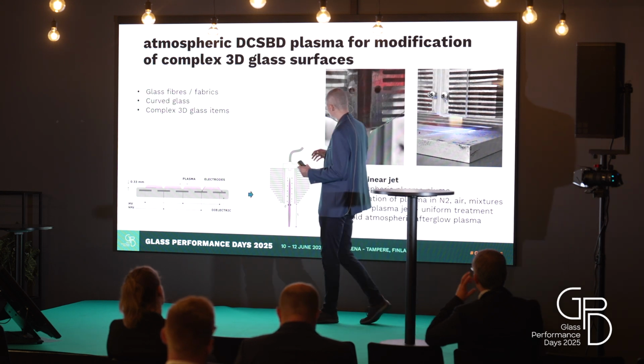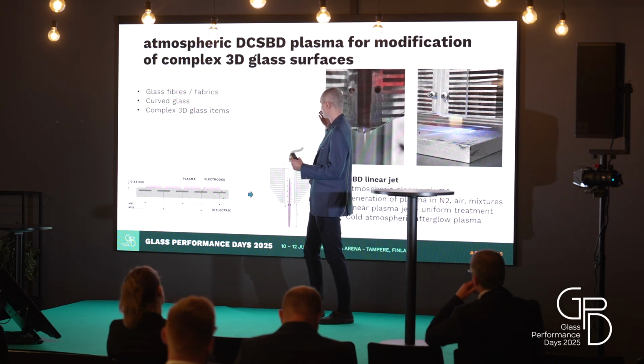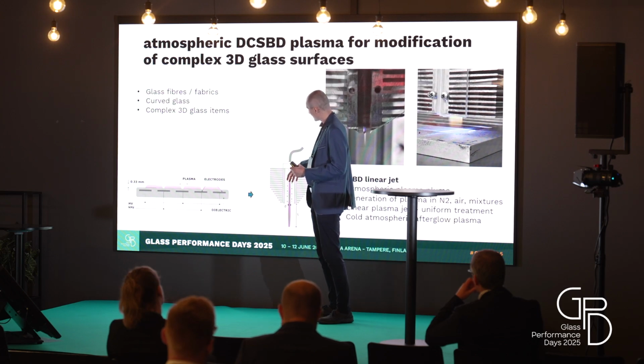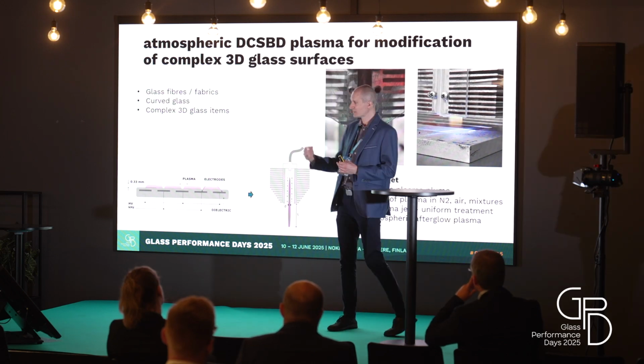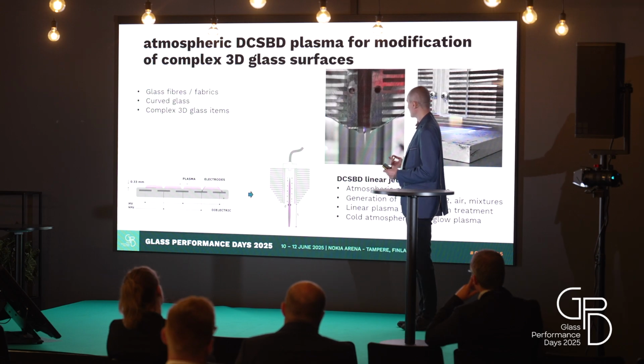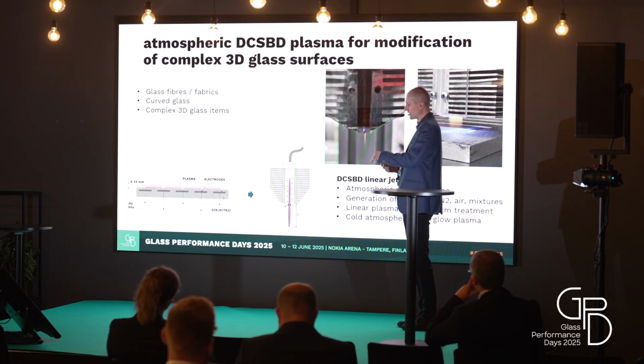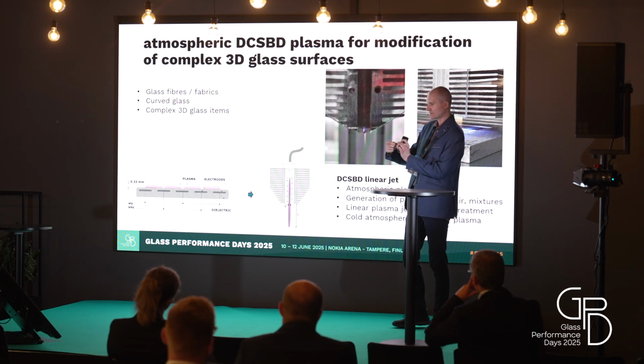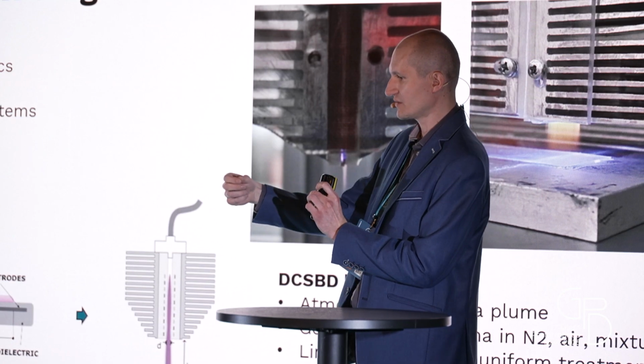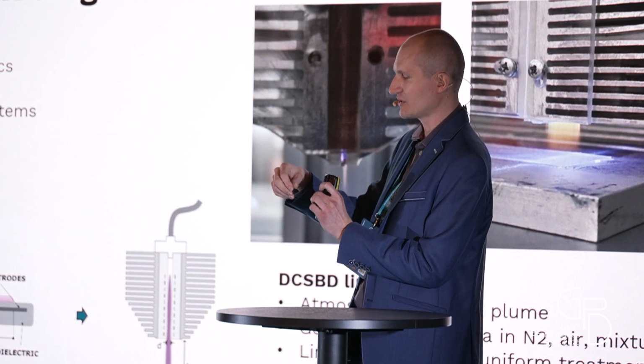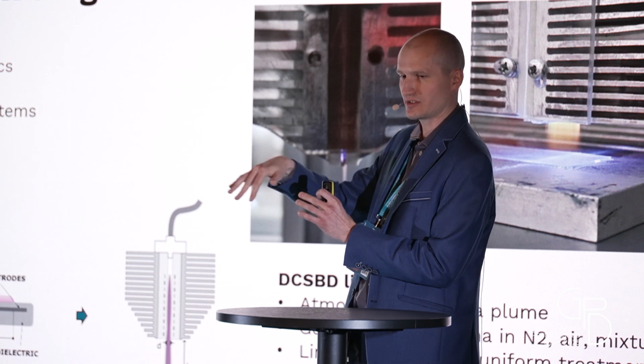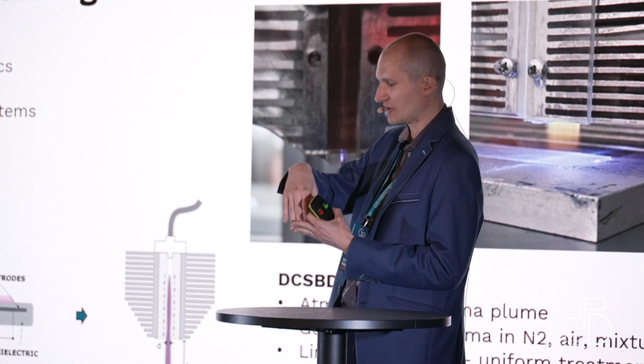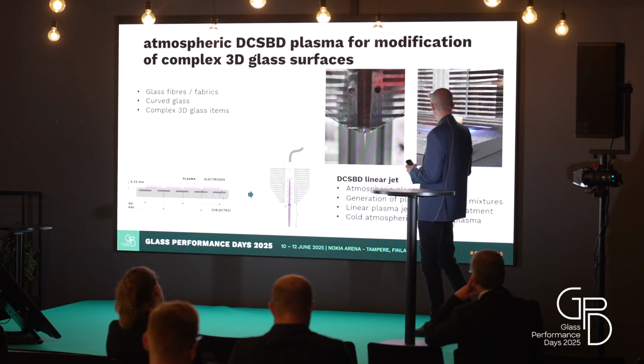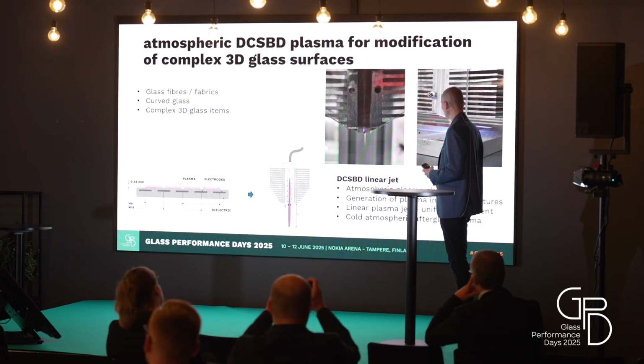And therefore, recently we developed a modified plasma system. It's based on the same technology, but this time we are generating a plasma jet. We call it a DCSBD linear jet, but in comparison to another plasma jet system where a point-like jet is generated, in our case we are generating a linear jet system. You can imagine it like a plasma curtain, which is suitable for line treatment of very complex material. Like here, we have a glass surface, for example.